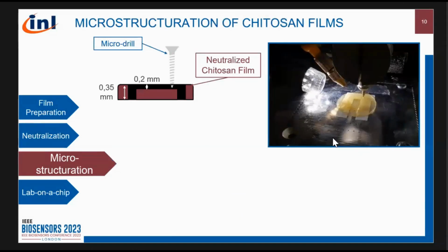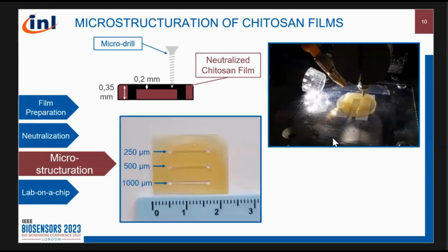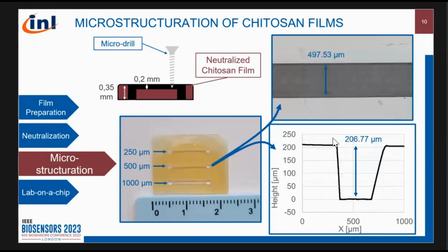Now we have a film that is not soluble in water anymore, so we need to microstructure it. We choose to use the microdrilling method, where you just need to drill the shape that you want on top of the Chitosan film. You can even drill holes through the Chitosan film. One advantage of this method is that you can vary the size, the width, and the height of the channels as you want on the system. You can obtain several of them. Here, for example, you have 3 channels with different sizes, from 250 micrometers to 1,000 micrometers wide. We characterize the dimensions by optical microscopy and profilometers to verify that we obtain the dimensions that we wanted.